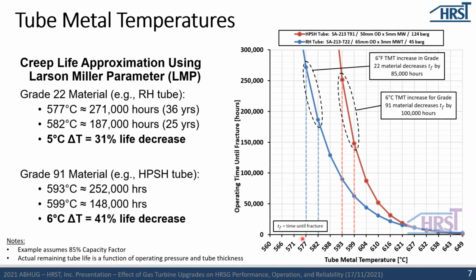For the second example, which is looking at a grade 91 material, typically an HP superheater tube, could be a reheat tube as well. Another fairly small change, roughly 5 to 6 degrees C, decreases the lifespan by roughly 41%. So when you're at these elevated temperatures, even a small increase in operating temperature can have a large effect on the lifespan of the part.